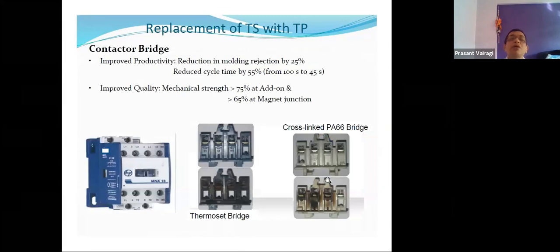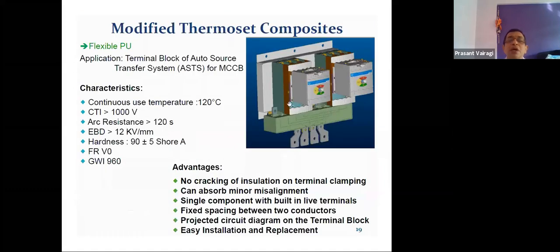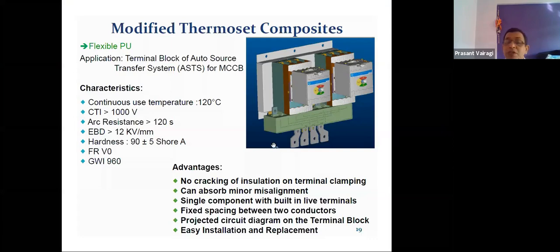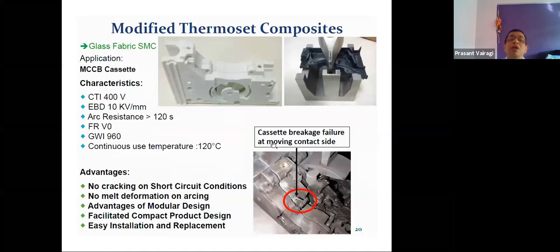Okay, the moment you go for modified thermoset composite, this is basically a modular design where we have gone for glass fabric SMC material. The fabric based material gives the longest length of glass fiber and orientation also in the desired direction, and hence it gives at least 100% higher mechanical strength compared to the traditional material. Nowadays even thermoplastic fabric based materials are available, and there is a hybrid molding technology where one can use fabric based material in combination with radiation cross linkable material, and you can convert thermoplastic material to thermoset, and you can reduce the size because these give exceptionally high strength. If I had to make this component with a traditional form, the size of the product would go up enormously high.